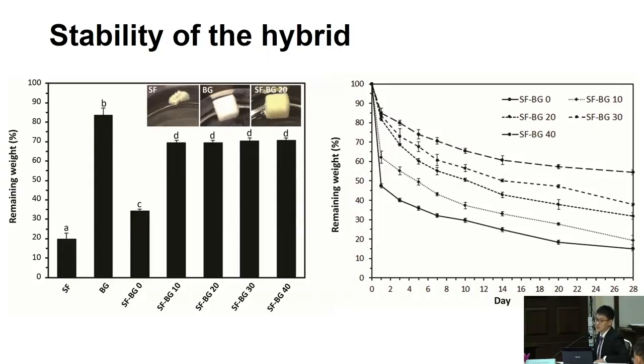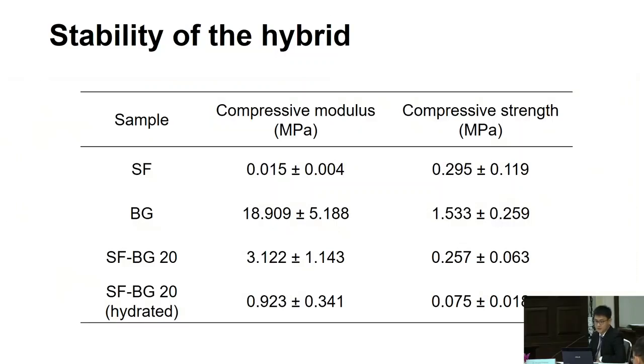And that is good because bone non-union could heal within 3 months. So if we can keep this percentage of the weight after 1 month, we have a high hope that in 3 months, these bone scaffolds can maintain their mechanical property and their structure to maintain the bioactive activity of the scaffold.